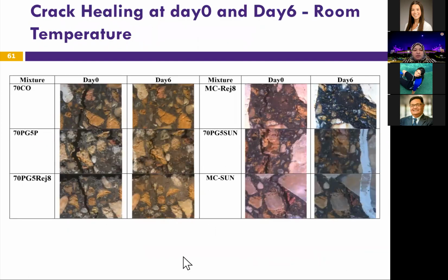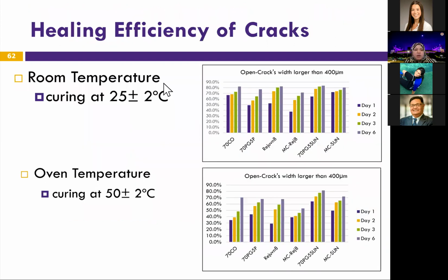This slide shows the different mixtures. So we had control and then control with 5% RAS. Then we added the first rejuvenator to the 5% RAS. And then we added the micro-encapsulated rejuvenator to the 5% RAS. And then this is the sunflower oil with 5% RAS, and then microcapsules, sun oil with 5% RAS. And if you look at the crack, after 6 days, there is significant healing in all of the specimens, including the control. The actual healing efficiency agrees with what you just saw visually.